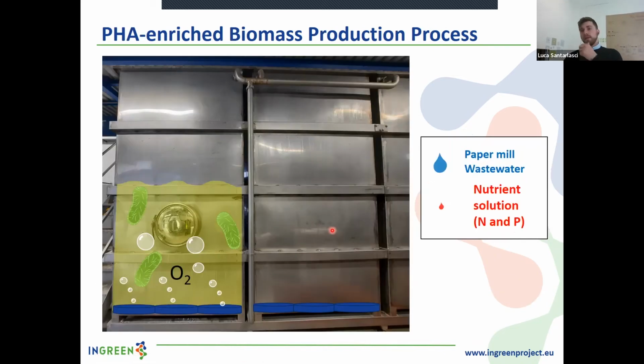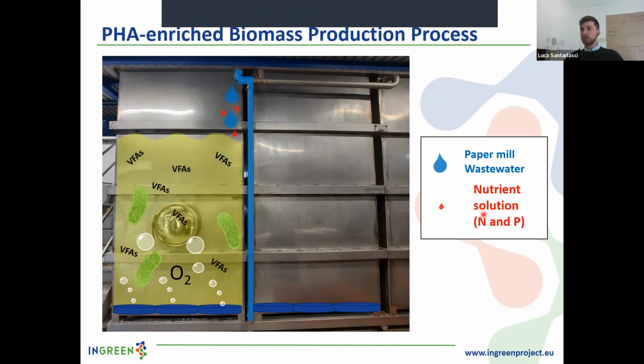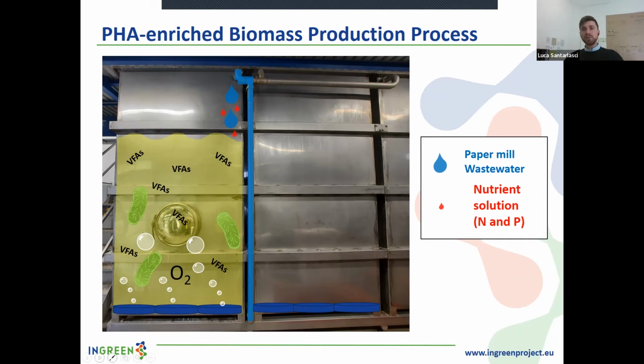In particular, during the feast phase, the paper mill wastewater and the nutrient solution, which contains nitrogen and phosphorus, are dosed into the SBR1, so the biomass starts to consume the volatile fatty acids in the paper mill wastewater to produce the intracellular PHA, and the dissolved oxygen concentration of the fermentation media decreases. When the VFA have been completely consumed, the dissolved oxygen concentration rises again, and the biomass enters the famine phase. In this phase, the bacteria start to consume the intracellular PHA to survive.